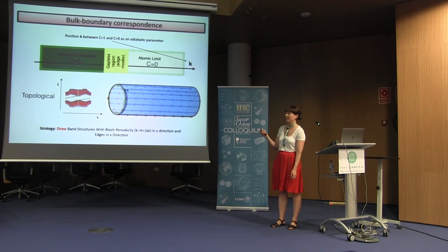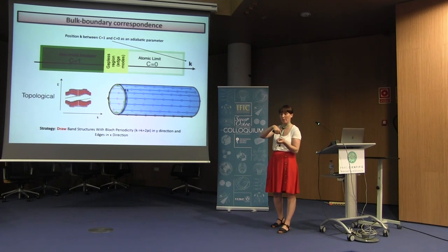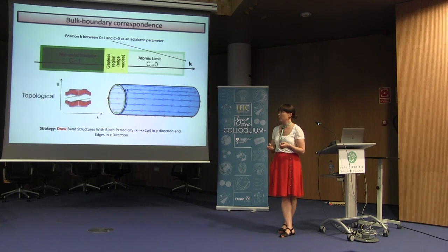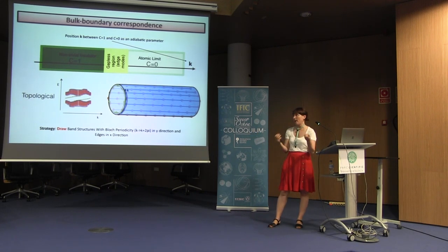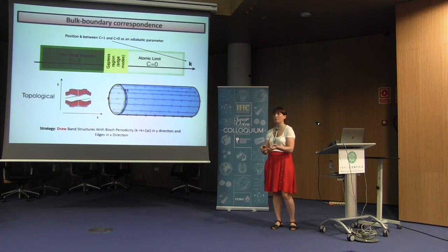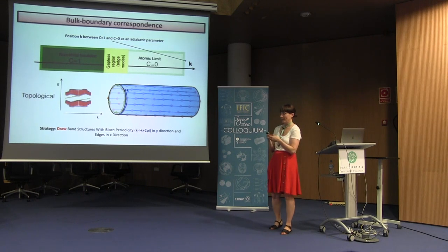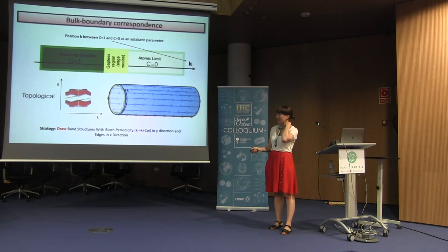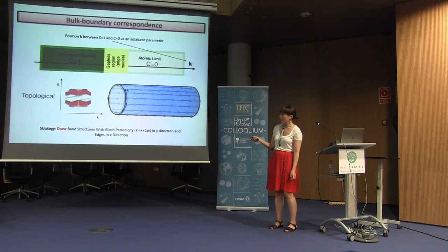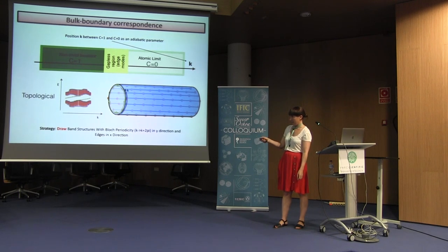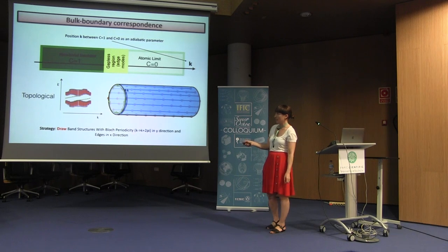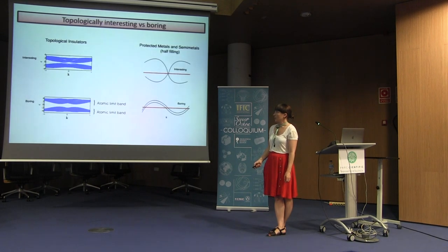The trivial insulators fulfill the atomic limit. It means that the electrons are close to the atoms. And what happens in non-trivial insulators is that they do not fulfill the atomic limit because the electrons somehow are away from the atoms. And because they are away from the atoms, when we break the translation symmetry, these electrons have to float. Another way of looking at it, when we look at the torus that I introduced before, is when we have a topological insulator, what the electrons do within the torus is a full loop. And these full loops make the connection between the valence band and the conduction band. When we have a trivial insulator, the electrons do not make the full loop. At some point, they go back, and the band does not connect the valence band and the conduction band.